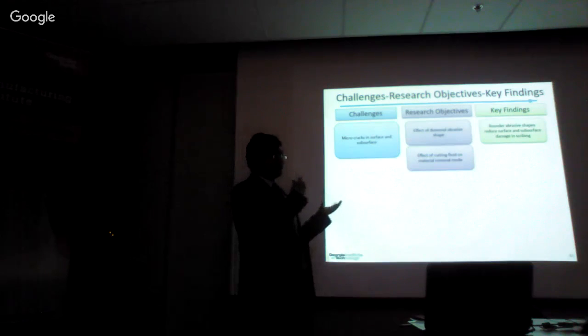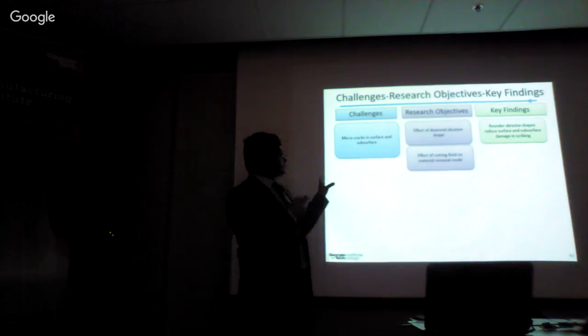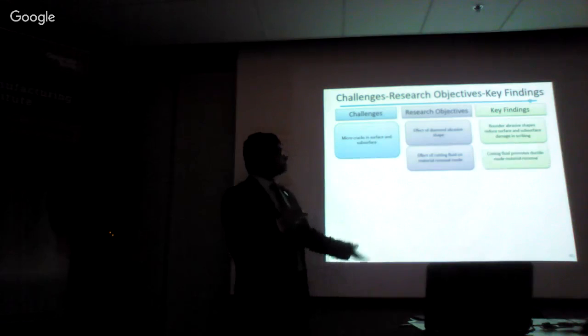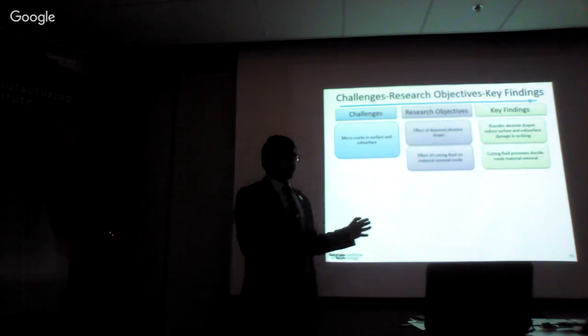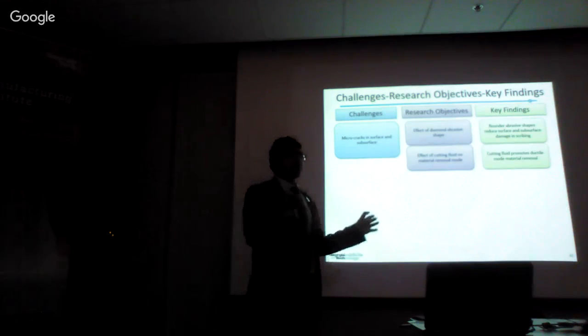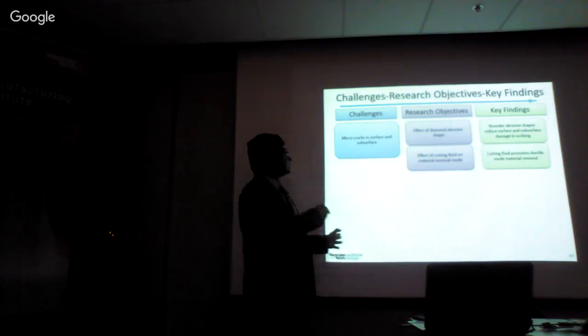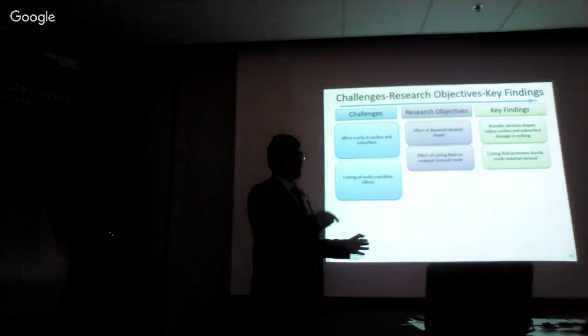Secondly, for the effect of micro cracks on surface and subsurface, which is one of the challenges, one of the research objectives was to find the effect of cutting fluid on the material removal mode being ductile or brittle. And we found using the cutting fluid and altering the chemistry of cutting fluid would promote more ductile mode material removal, thus reducing the micro cracks.